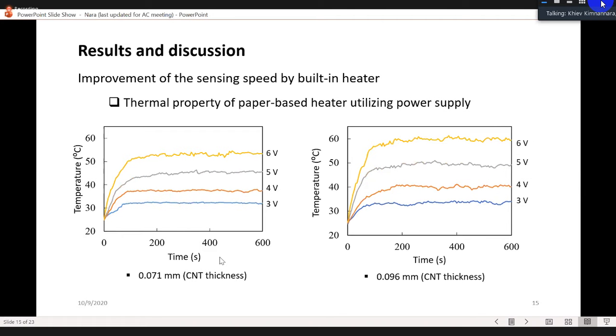And then for 0.071 millimeter, we can increase the temperature more, to around 32 degrees Celsius when we apply 3 volts, and it can reach around 50 when we apply 6 volts. For the highest thickness of CNT layer in my study, I coated with 0.096 millimeter of CNT thickness. I found that the temperature can be increased more to around 33 degrees Celsius when I apply 3 volts. Then it reached almost 60 degrees Celsius when I apply 6 volts.